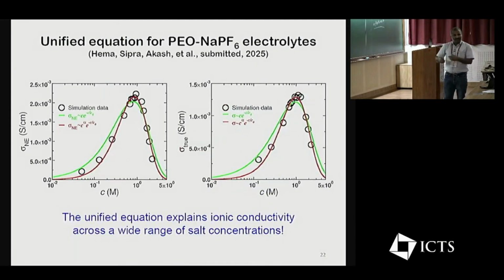We also applied these ideas to a newly emerging electrolyte, sodium-based polymer electrolytes. This is a completely polymer electrolyte, and we still find a nice fit with the simulation data using this C to the power alpha exponent kind of improvement.